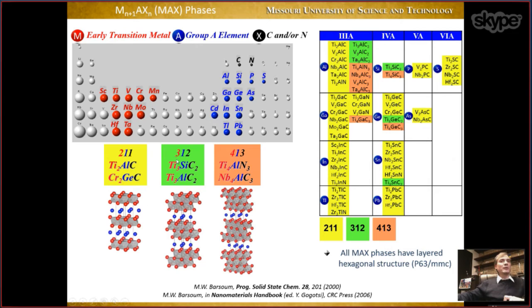They can be 5 atomic layers thick, where we have M element, X element, M element, X element, and M element. So this is our MX block. And then the A element layer. Or they can be 7 atomic layers thick, okay? So you already start to get a feeling that the number of these MAX phases is quite large, right? They differ in terms of M elements, A elements, and the thickness of the MX blocks, and the number of MAX phases right now is more than 70, okay?